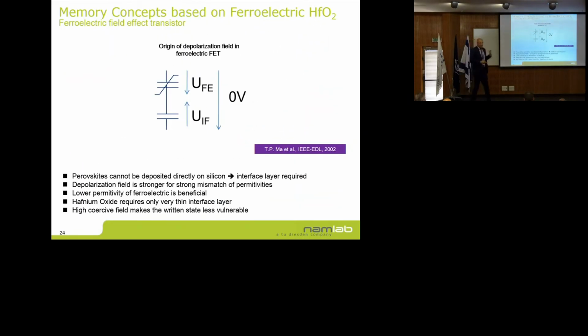Another thing that is very important, it is of course a very natural idea of integrating the ferroelectric in a transistor. So why haven't we seen that? People have tried for decades to realize that. But if you put the ferroelectric in series with another dielectric that you need to have a stable interface to silicon, you will have a depolarization field which kills your retention. So there's this famous paper from T.P. Ma telling you why ferroelectric field effect transistors are still elusive.